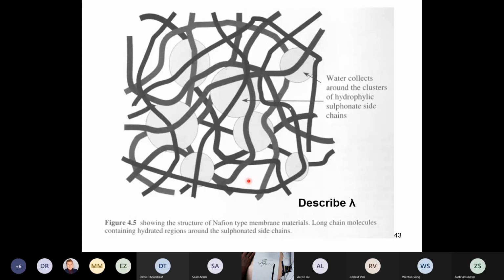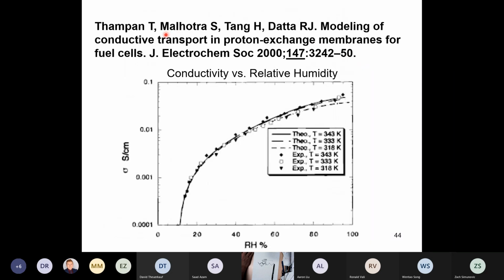So this is a cartoon that shows the long chain of the polymers, and the water collects around the clusters of the sulfonate side chains. And you want to have these waters overlapping so that the proton conductivity is really good. And here's a graph that shows you the conductivity versus relative humidity. It's a log scale for conductivity for different temperatures. Remember, the fuel cells are going to operate up around 80 degrees C. So this would be 70 degrees C. 343 is 70, 333 is 60, and 318 is whatever it is.